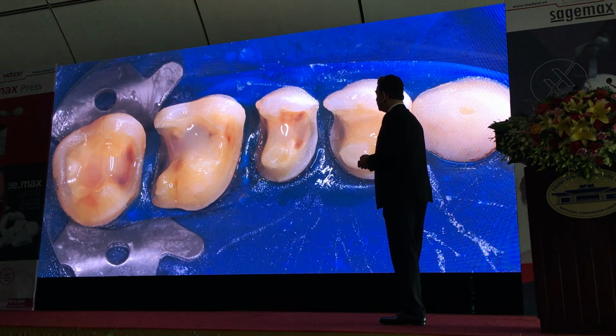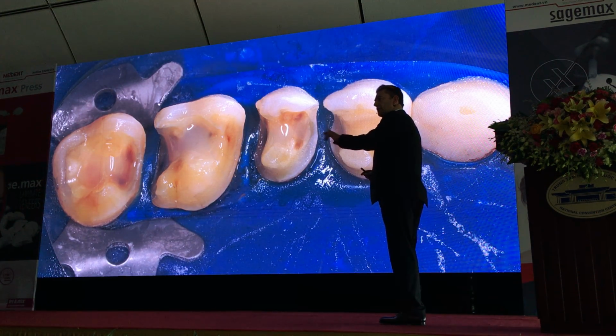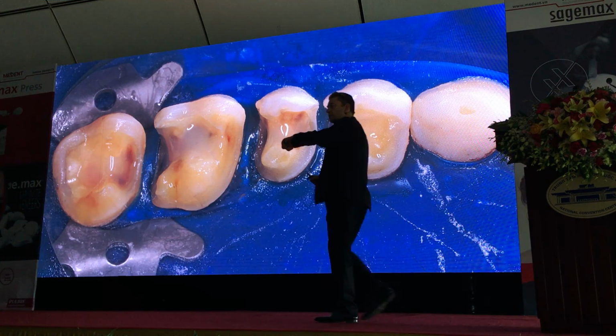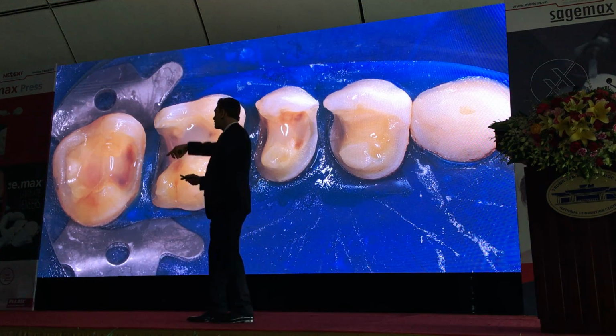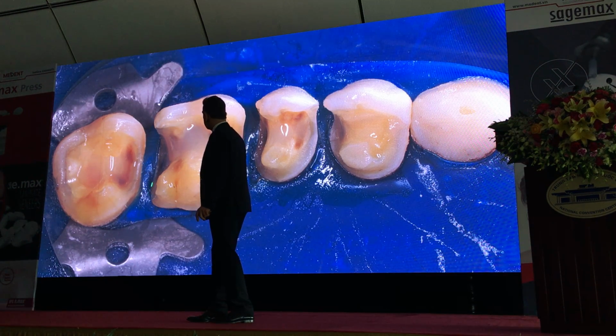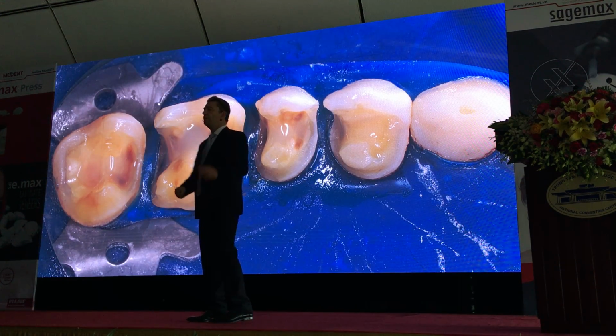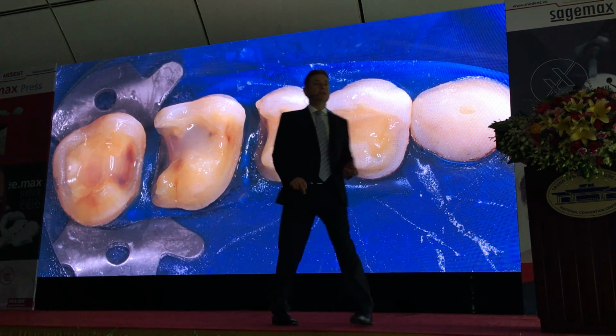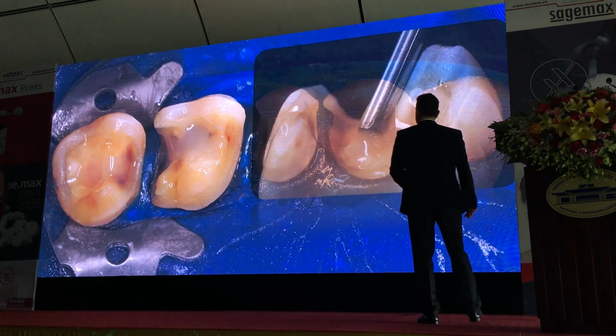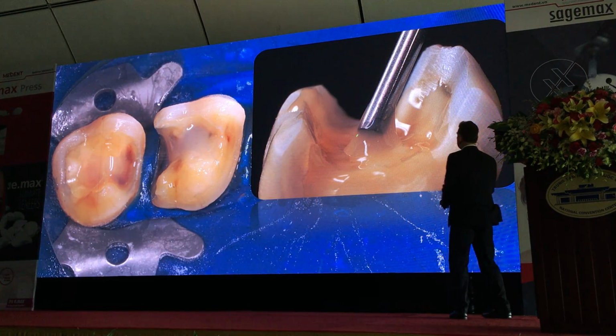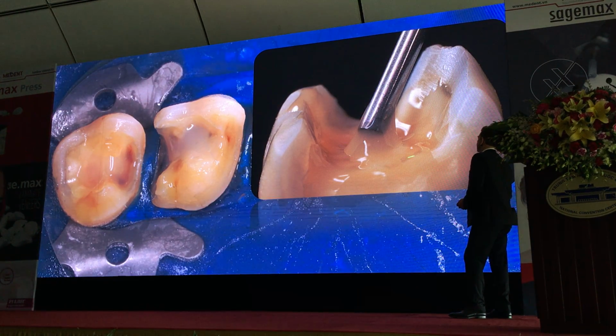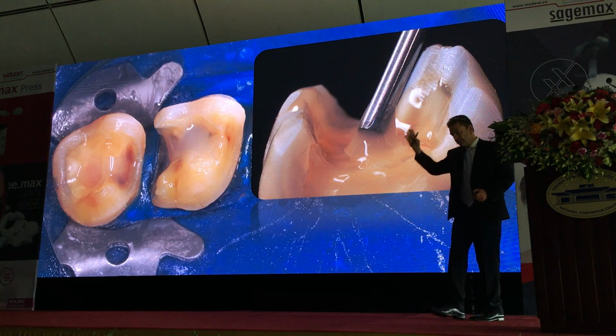So for example, you can use a flowable. When you have some undercut here, you can spread the flowable inside the undercut and you cure it. And then before you take the impression or the scan, you can just finish your enamel so that you don't have any composite on your margin. Okay? And this is a very good technique where you will not have any sensitivity. Okay, so you can see this with the flowable. You can of course cover this, but if you have undercuts, you can also spread the flowable into the undercut and then you block it out.